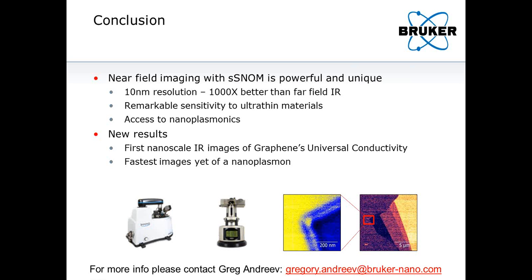A question here: is tip heating a problem if you have, say, a low melting material, maybe a polymer that melts relatively low? Tip heating is usually not a problem because the laser powers we are using are below 1 milliwatt. That's all you really need to get enough signal, and that's how much laser power goes into the interferometer. That's ultimately focused to about a 10 micron spot on the tip, but it does not affect the tip. I can observe this experimentally by looking at the tapping amplitude of the tip, and if I observe no major changes, there is no significant tip heating.